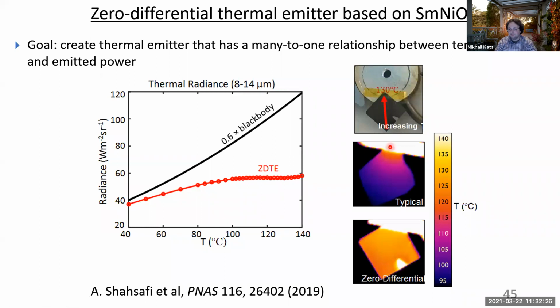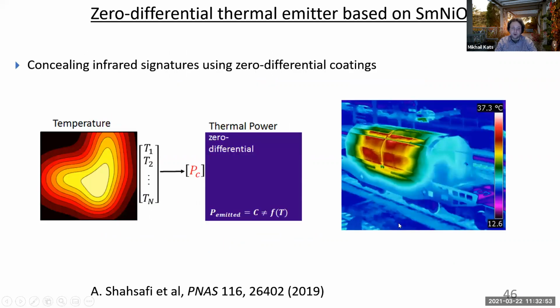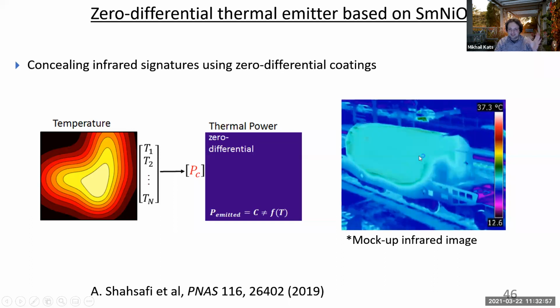If you take a typical wafer, here it's a piece of sapphire, you can immediately see this temperature gradient on an infrared camera. Whereas over here on the zero-differential sample, you don't see anything at all, because even though this place is hotter and this place is colder, this place has lower emissivity and this place has higher emissivity to balance that out. And this happens automatically. So you end up having no spatial information for this infrared camera. We think this is interesting and exciting for infrared privacy and camouflage type applications, where we can try to conceal things.